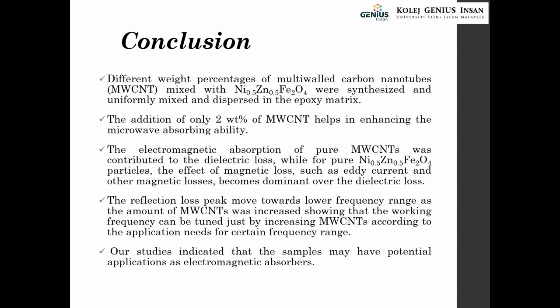For conclusion, different weight percentages of multi-wall carbon nanotubes mixed with nickel zinc ferrite were synthesized and uniformly mixed and dispersed in the epoxy matrix. The addition of only 2% of MWCNT helps in enhancing the microwave absorbing ability.